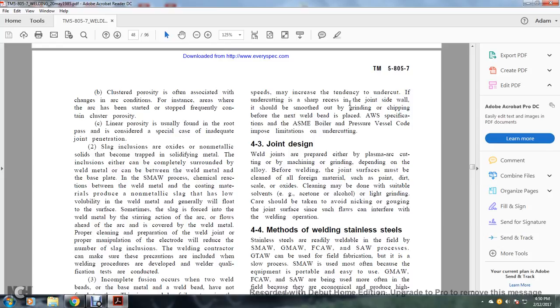If the undercutting is sharp and recessed in the joint side wall, it should be smoothed out by grinding or chipping before the next weld bead is put in place. The American Welding Society specification and the American Society of Mechanical Engineers Boiler and Pressure Vessel codes impose limitations on undercutting. 4.3 Joint design.